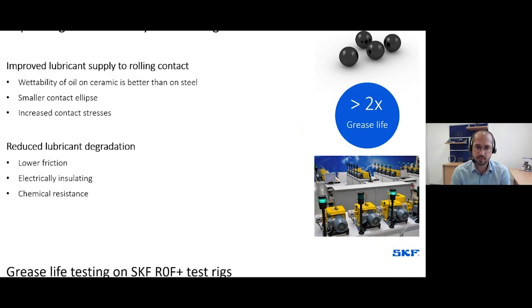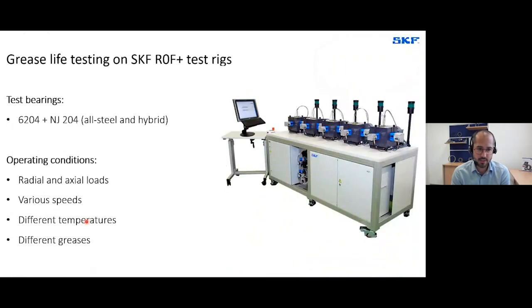Because we have done extensive grease life testing on our SKF ROF+ grease life test rigs. And we certainly know how grease life behaves or how greases behave in hybrid bearings. So we have tested deep groove ball bearings and cylindrical roller bearings, and we have compared steel and hybrid bearings. We have carried out tests in different loading regimes, at different speeds and temperatures. And very important, we have also done those tests on different greases.